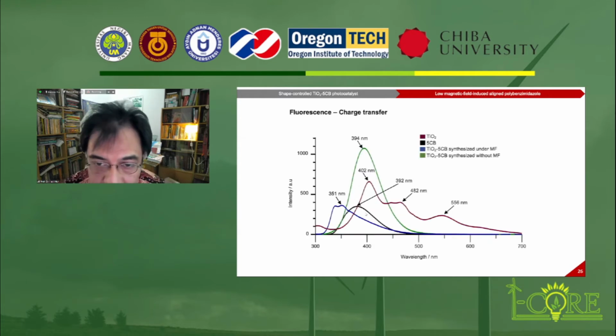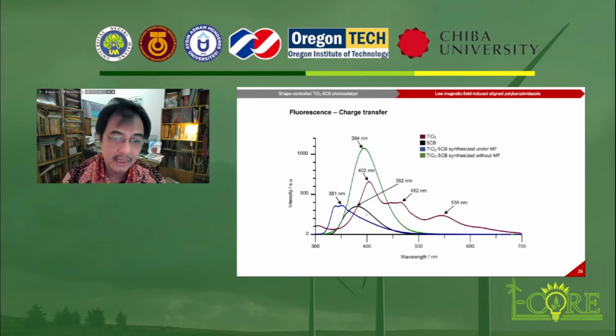This is the photoluminescence spectra of the titanium dioxide 5CB sample synthesized under a magnetic field and without a magnetic field. It can be seen that the sample synthesized using a magnetic field shows a new peak here at 350 nanometers. This is due to the unique charge transfer of this material caused by interfacial interaction between the titanium and the liquid crystal. To elucidate this, we use DFT, density functional theory, to explain it.